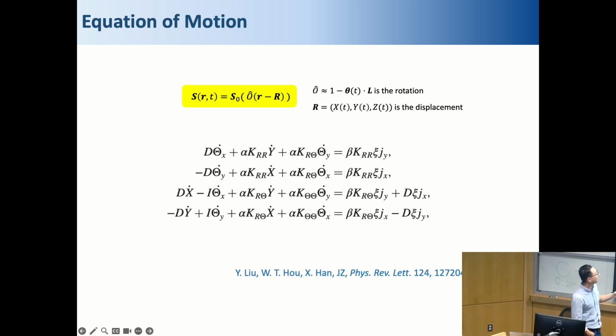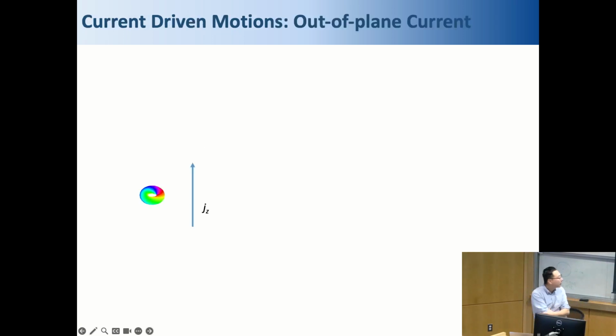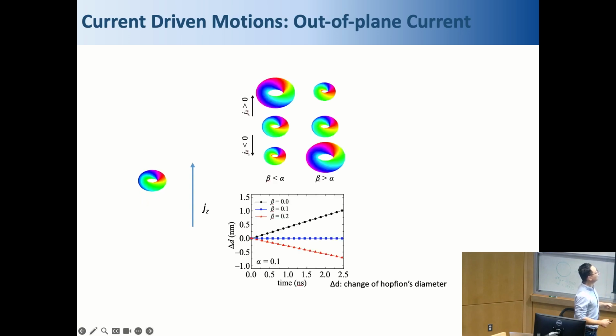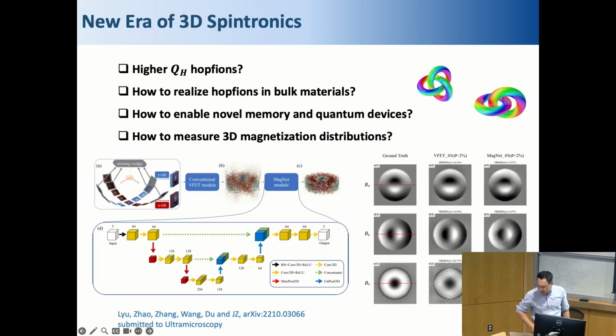It's complicated, right? So theta x, theta y are just rotation angles. X, y are the transverse displacement of the hopfion. And in a very special case, if we apply current perpendicular to this torus plane, this hopfion will move and start to expand. If you apply an opposite current, it just shrinks. So this can also be modeled as well. The last message is we are seeing some interesting configurations in 3D.